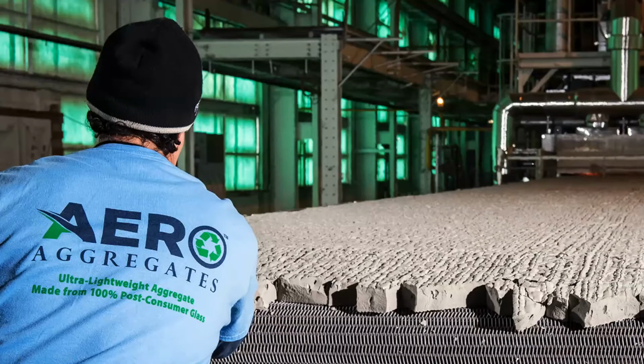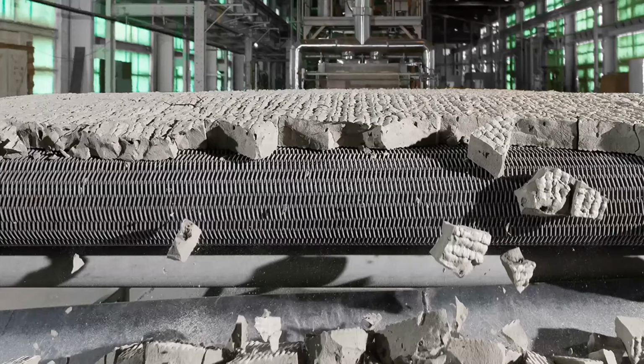And if you were to walk along the cooling table with the product, you would be hearing this snap, crackle, and pop sound. And what that is, because of the temperature differential from being in almost a 1,000 degrees Celsius kiln to then being exposed to, say, around 20 degrees Celsius room temperature air, that is inducing thermal stress into the foam glass cake, and the cake starts to crack up. So by the end of the cooling belt here, we've already created these aggregate sized pieces that are going to fall onto the conveyor, as you see here, and head outside.